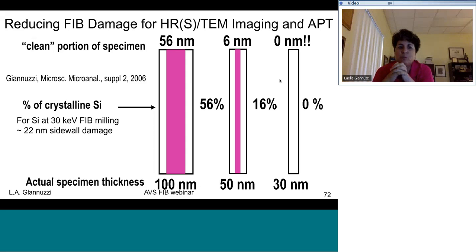This is really important when we want to reduce beam damage for high resolution S/TEM or even for atom probe tomography. So we know that if we take, for example, silicon and use 30 kV gallium on each side, this is going to result in about 22 nanometers of sidewall damage per side. So if we have a 100 nanometer thick sample, that means only the center 56 nanometers or so is totally pristine. Or I should say, not necessarily pristine, but not amorphous, okay?